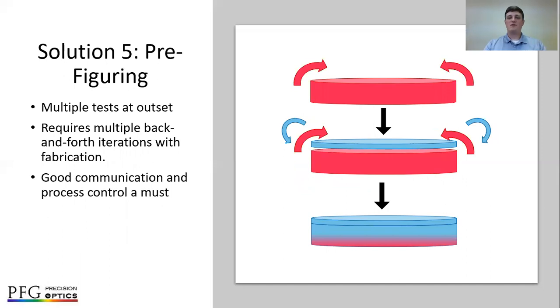And lastly, if no solution can be found to maintain the flatness, it may be necessary to prefigure the parts. That is, the flatness change due to the coating is characterized, and the inverse of that is polished into the substrate, such that after the coating is applied, the optic is bent into a flat nature.